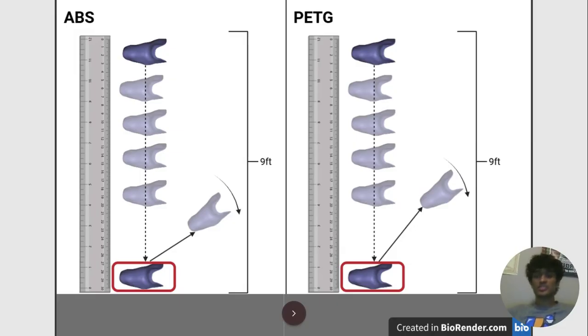The next test conducted was a drop test to test impact resistance. In this test, the number of drops was calculated and it was measured. Each prosthetic was dropped from a height of 9 feet, and as you can see, each prosthetic tended to bounce up, but PETG bounced up higher than ABS did.